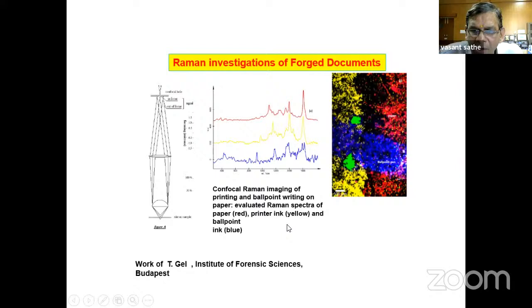I think this printer ink is yellow and ballpoint ink is blue, and the paper also gives Raman spectra. So this paper gives this type of Raman spectra, and the printer ink is yellow. So this is the Raman spectra, and this is this. So you do Raman mapping, and you see that my printer ink is mostly below this blue ballpoint ink. It means this is not a forged document. If you take a printout over it, there will be very small toner particles over this blue ink. And there are some small things visible over there, but they are not remarkable. In this way, you can very easily find out whether the person has taken the printout first and then taken the signature.